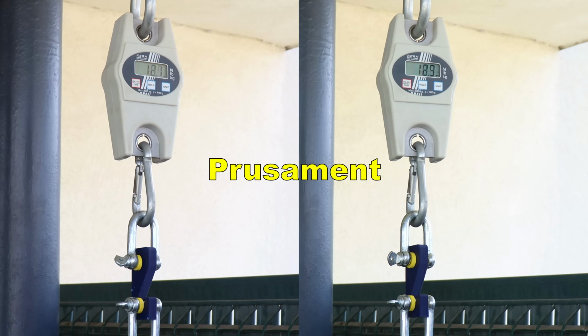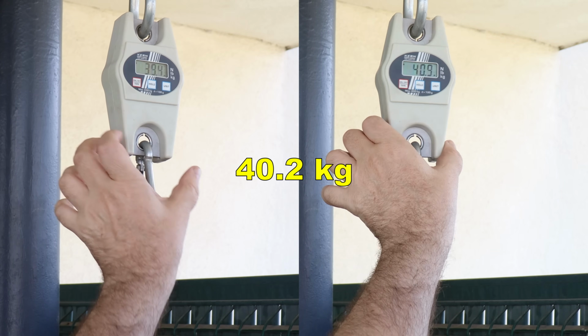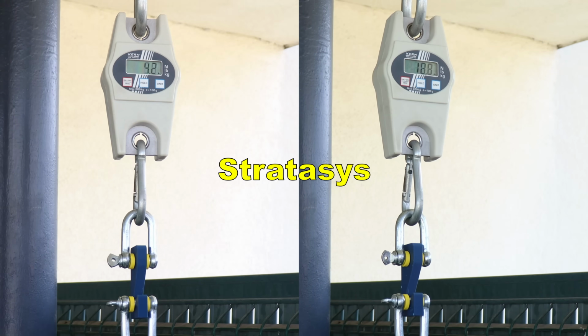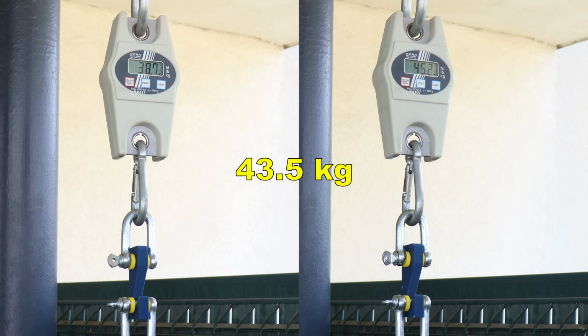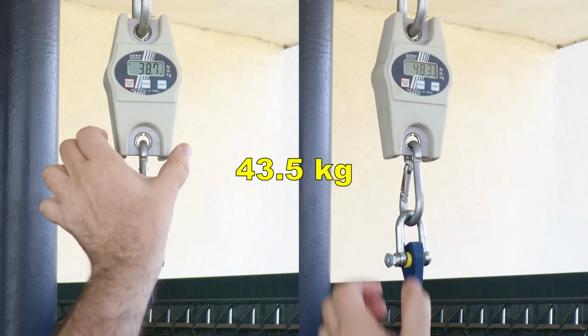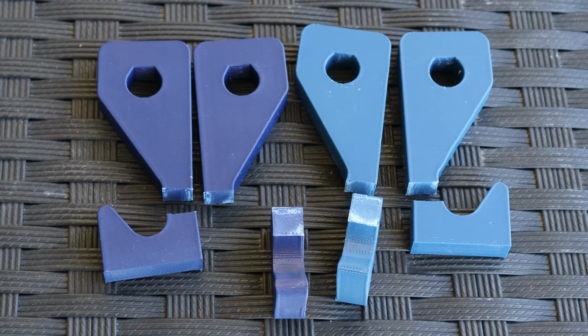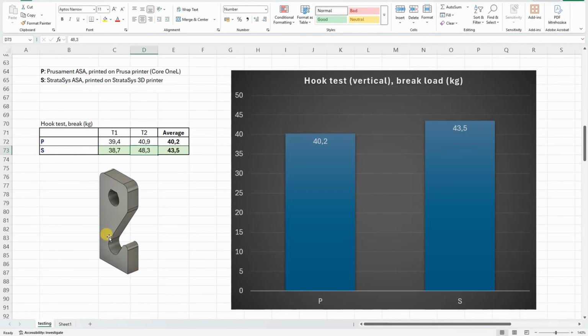Hooks printed in vertical position. And now Stratasys, 2 hooks. The break was very similar in all 4 cases. These hooks are printed in vertical positions, so the layer adhesion is important here, and we can see a small advantage on the side of the Stratasys ASA compared to the Prusament, but what I don't like here is this big difference. These two are much closer to each other, so if this Stratasys were printed by me, I would print at least 3 more test objects for better accuracy.